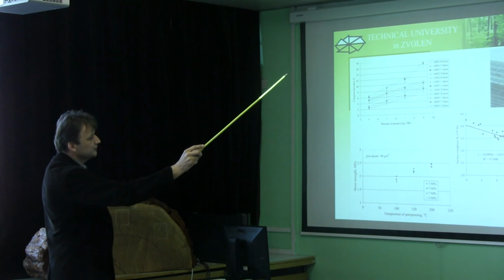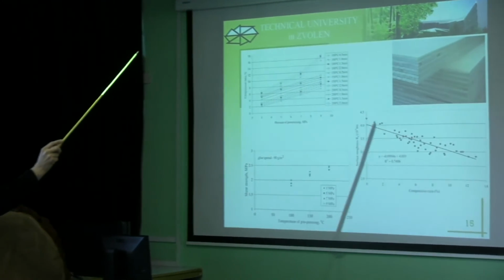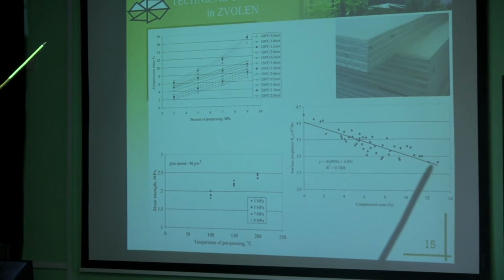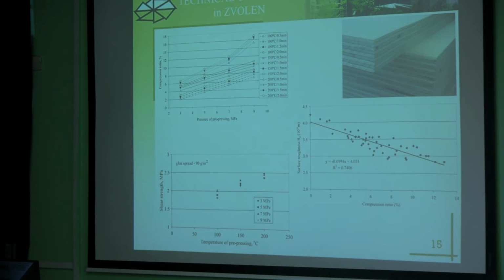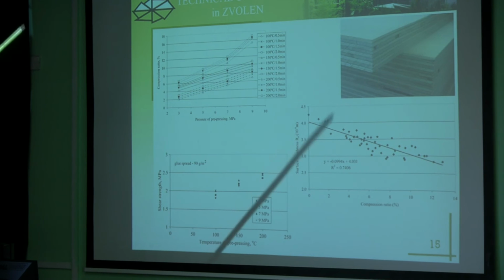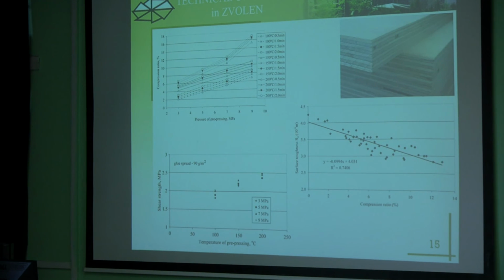Here is the surface roughness, and we can see the degrees of the surface roughness. Here is the regular sample, and we see that the compression ratio about 12%. We can see that the roughness is maybe only half of the previous state. This is the positive effect of quality at gluing of plywood, because this plywood was glued by phenolformaldehyde adhesive, and as I mentioned before, phenolformaldehyde adhesive is chemical setting resin, and there are created a lot of chemical bonds between the adhesive and the wood substrate, between the veneer, and also there is very good absorption of adhesive on the wood, or wettability of the adhesive on the wood surface.